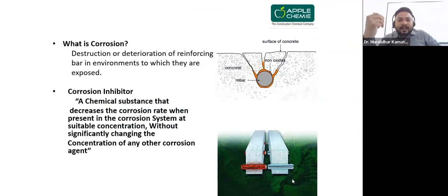So how the action works over there. Whenever your reinforcement, rebar, is there, generally, I'll talk about it as Fe2+ valency. I'll keep it simple. Fe2+ valency, right? When Fe2+ is getting in contact with the moisture, that valency changes from Fe2+ to Fe3+. Means volume expands, and that will create a crack at your concrete surface, and deterioration happens over there, because corrosion initiation will start and it will deteriorate your concrete.